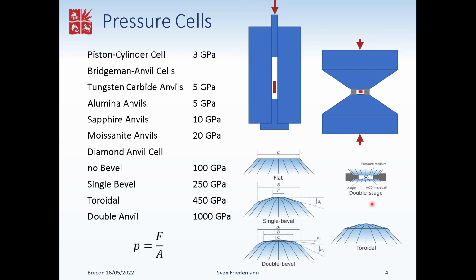There is a good reason to actually use synthetic diamonds, because they are more reliable and lower in impurities, which is good for many experiments. I'll talk about that later. But also, I've made the case that we need to go small. One could now say, okay, let's just scale everything by a factor of 2, including the force, and hence you would still get the same pressure. But that doesn't work, because you'd also increase the number of imperfections in the diamonds by 2 or 4, if you think about area and volume. And hence you've got more likely a failure. So it doesn't work by going bigger. So impurities are an important consideration. So that's a case for artificial diamonds.